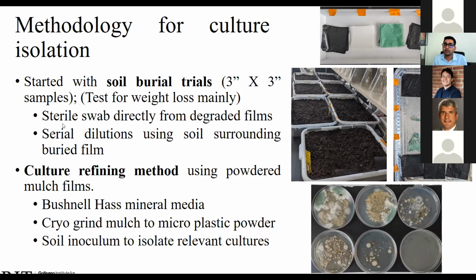The isolation of microbes was done 2 ways. One was using a sterile swab directly on top of the film. So we would swab the film exactly on the top and isolate the microbes directly from the film. And second was to actually use the soil just around the film and serially dilute it to get 10 to the -6 dilutions. This is just a sample plate of what we got using soil, and similar would be what we get using the sterile swab. So the plates on the top here show fungal cultures, and you can see different types and varieties of fungi growing as you would expect.